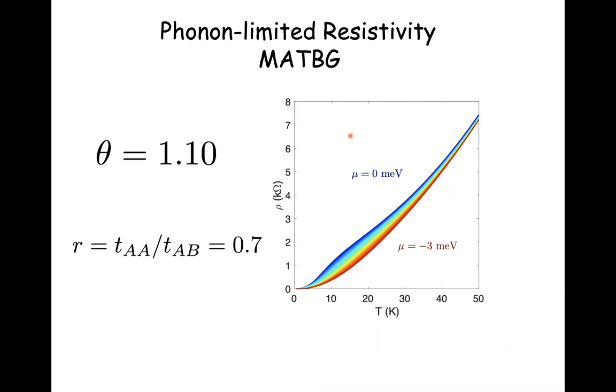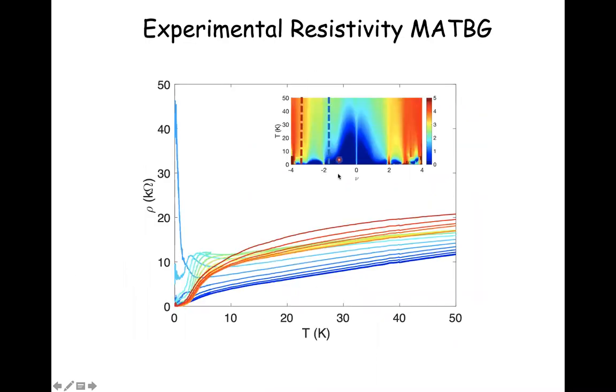Okay. Yeah, so I won't discuss this in detail, but the resistivity is also strange, hard to understand in terms of Fermi liquid, especially near these jumps in Hall density. You can calculate what the resistivity would look like as a function of temperature. If you had simple phonon limited resistivity, the resistance gradually goes down as you make the Fermi surface bigger. That's not at all what happens experimentally. Instead, as you put in more carriers, the resistivity goes down, but then as you approach this region where the Hall density jumps, it starts to go back up again.